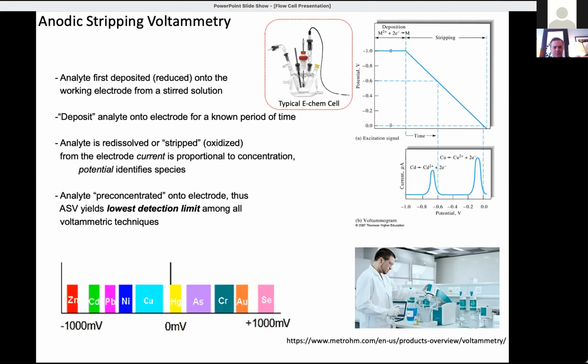This is done by applying a potential where the ion will spontaneously be reduced to the metal and be captured onto the electrode. And you can vary this time in order to change the sensitivity of the technique and the potential to target the specific species. These species reduce at different potentials. But we're not using this primarily as the detection technique. We're using this as a concentration technique.